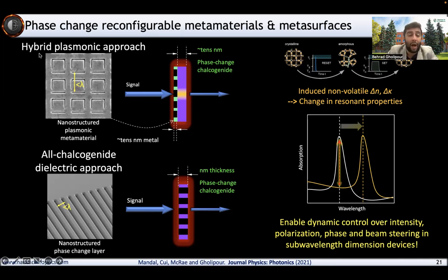We can either do this in a hybrid way by combining chalcogenide with a metal, or you can take the high refractive index of the chalcogenide itself and cut out the costly gold or silver, that's the major cost component in these devices, and nanostructure the phase change material itself. This allows you to get very nice resonances that you can switch again without the need to use a plasmonic metal in the device. This allows us to have dynamic control over intensity, polarization, phase, beam steering, and absorption and other things in sub-wavelength devices.